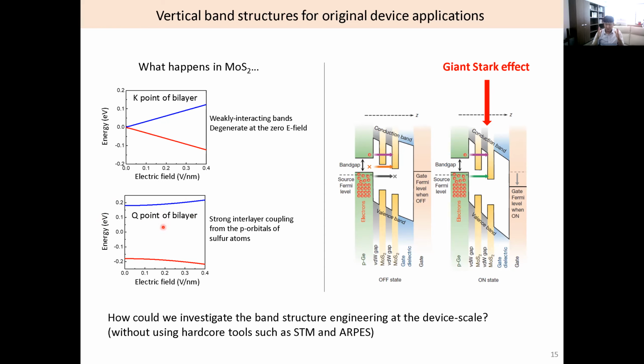There is a certain momentum, and then they have quite a strong layer-to-layer interaction by p orbitals of sulfur atoms. Sulfur atoms are relatively closer than molybdenum atoms. So they have high interaction, and once they form this bilayer MoS2, it's like a bonding, anti-bonding. They make a two-state, like a chemistry. And then these two states are not affected a lot by electric field. So this is mainly for Q-point electrons.